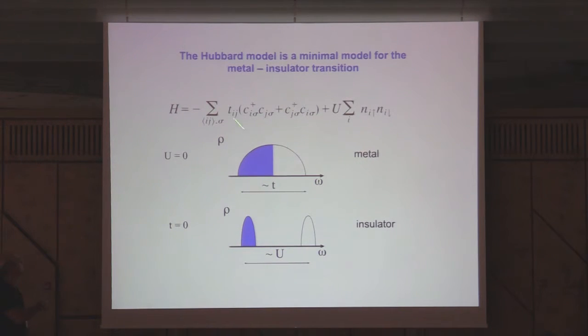On the other extreme, when there is no t, you just have an atomic Hamiltonian. And if you put one particle per site, you have a fully occupied flat band with a charge gap of the order of U. So you see that at least the two limits are OK. You have a metal and an insulator. Now, to solve this deceptively simple model in 1D: the moment you put a finite U, immediately it opens a gap. So clearly, that cannot be the experimental situation where you have a metal-insulator transition. So it has to happen at intermediate values.